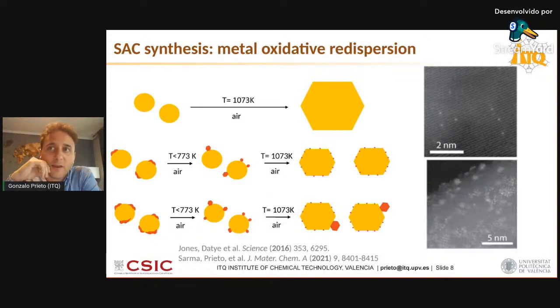It has been applied in industry for decades to redisperse supported metal catalysts that had undergone deactivation due to metal sintering and agglomeration. And we combine those oxidative redispersion phenomena to oxide supports, which have the capability to capture and stabilize mononuclear cationic species at high temperatures and under oxidative conditions. So in a nutshell, how does that go? If you look at the